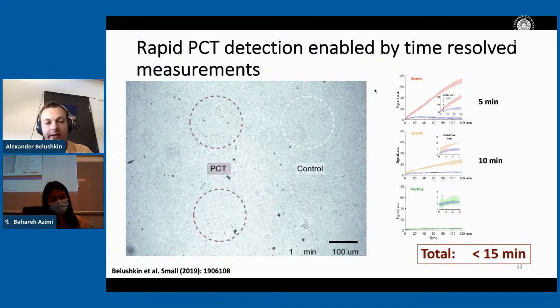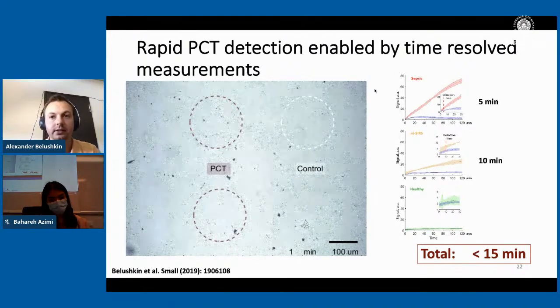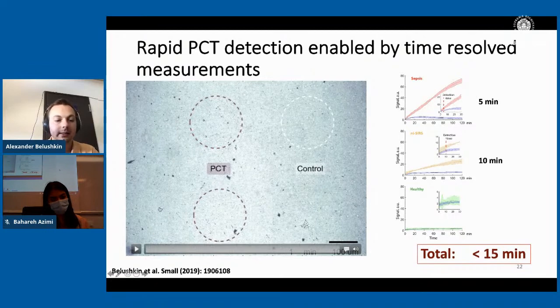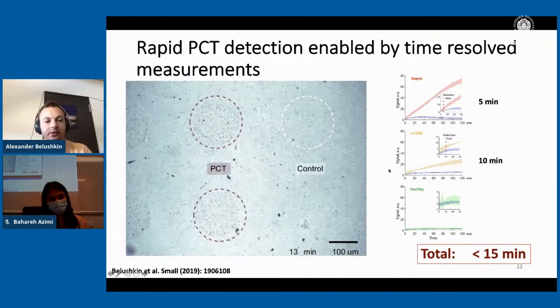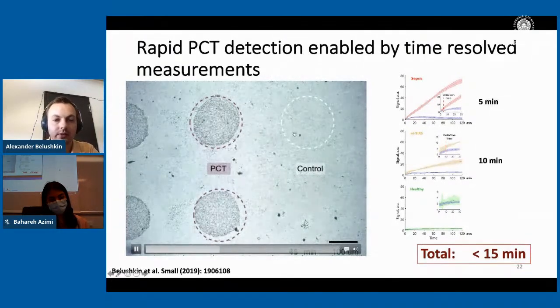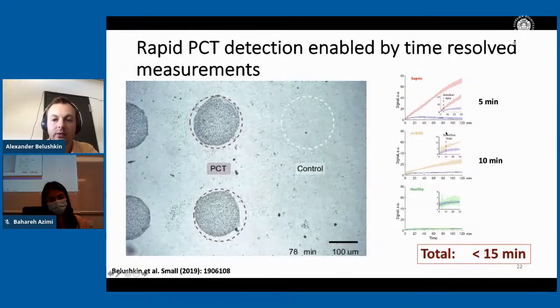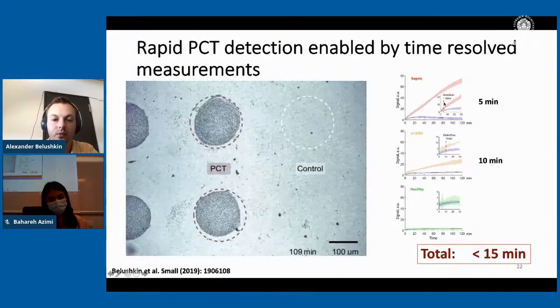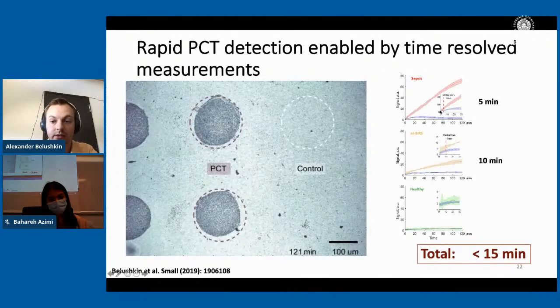So finally, the point was to show the rapid detection of biomarkers. In order to do that, we can in fact perform live analysis. So basically we take a video and we plot the signals in real time from the spot versus the control background. And then we can have the cutoff time where the signal exceeds the background and compare it for the sepsis, SIRS, and healthy groups. In this way, we can see that septic people we can identify within 5 minutes.